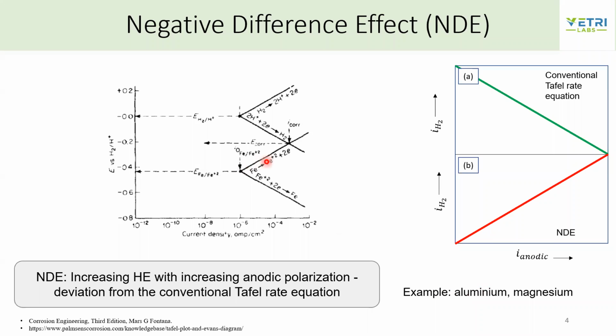So with that in mind, let's see what negative difference effect is. If we take this potential as the corrosion potential, anodic polarization is basically moving forward like this. And what we see is as we move forward, the hydrogen evolution reaction should actually decrease. This is what we would expect according to a standard Tafel rate equation designed based on the Butler-Volmer equation.